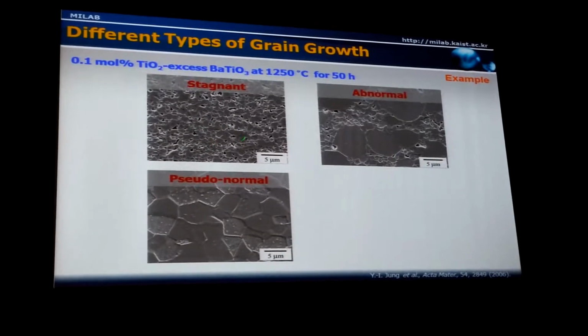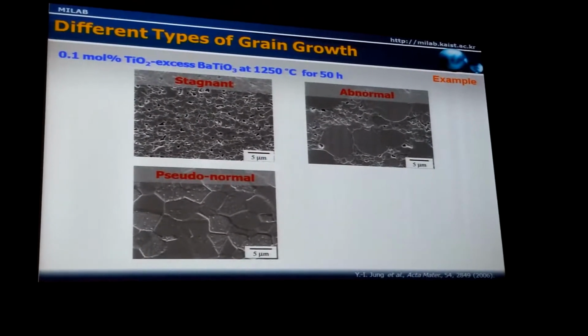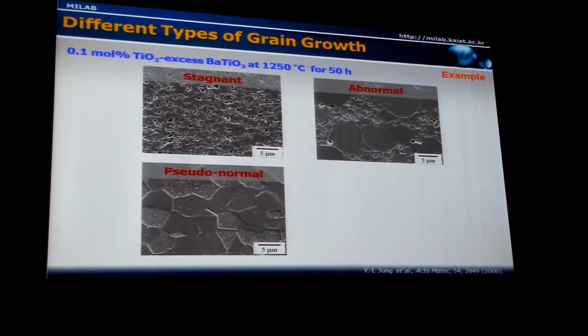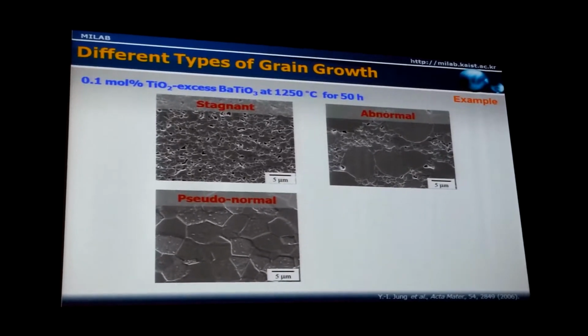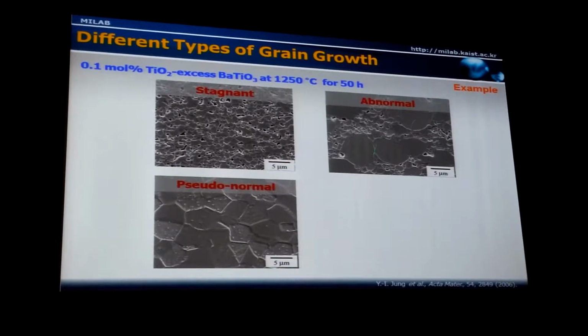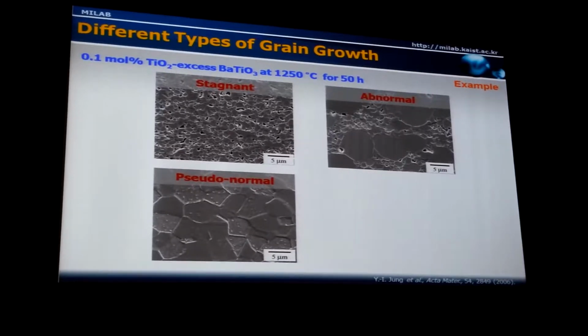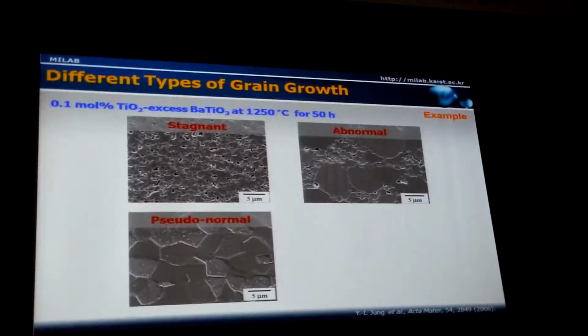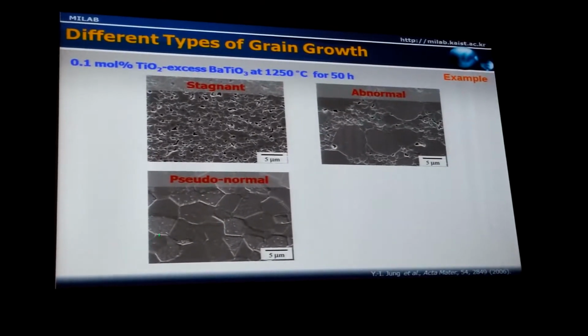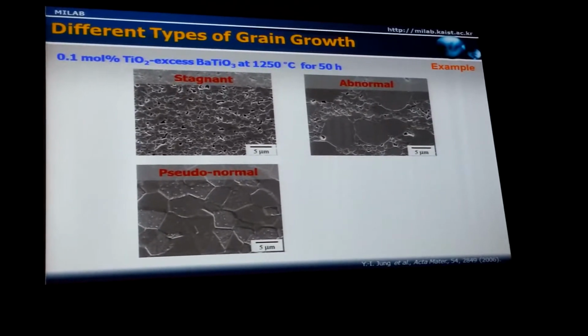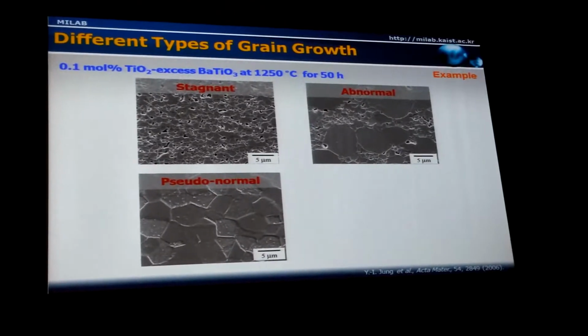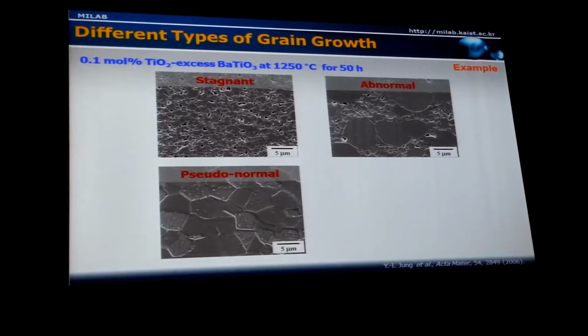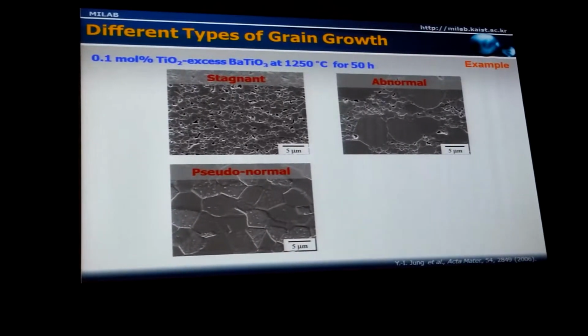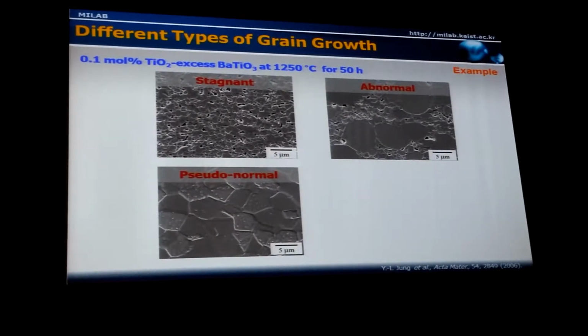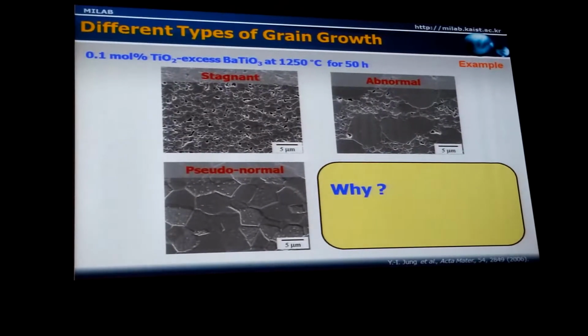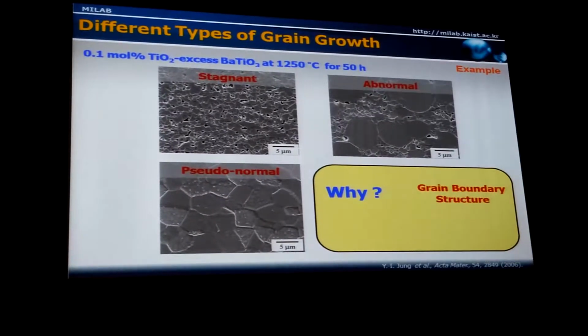On the upper left, we have very fine grains, and when we held this sample for a longer time, up to 100 and 200 hours, there was no grain growth, no change in microstructure, showing stagnant grain growth behavior. On the upper right, you see big abnormal grains embedded in a fine matrix, of which the size is about the same as that in the sample showing stagnant grain growth behavior. On the bottom left, the grain size is moderately large. When you held this sample for a longer time, grain growth occurred continuously, showing more or less normal grain growth behavior. Why such a big difference in microstructure and grain growth behavior in the same material after the same thermal treatment? My answer is it's because of a difference in grain boundary structure.